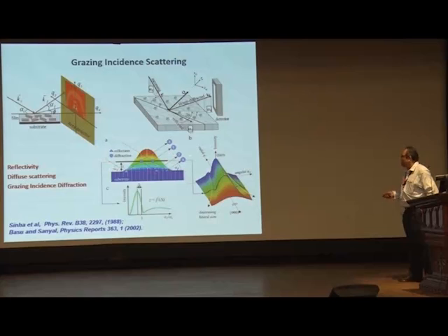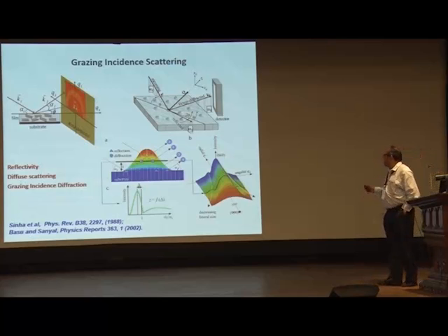The X-ray comes and gets scattered from the surface. It gets scattered from the quantum dot, and of course the nature of scattering can be of various types, which can be summarized in these 4 types, and these are details. And then by measuring all the X-ray scattered beam on a detector, you can figure out the composition of this quantum dot and also the shape of the quantum dot. That is what I'll convince you.